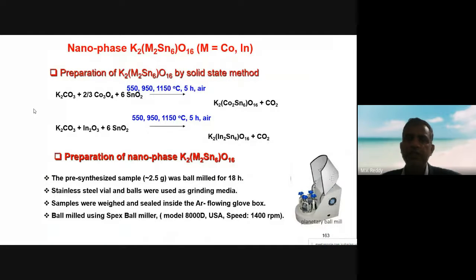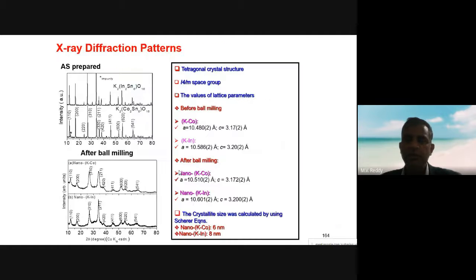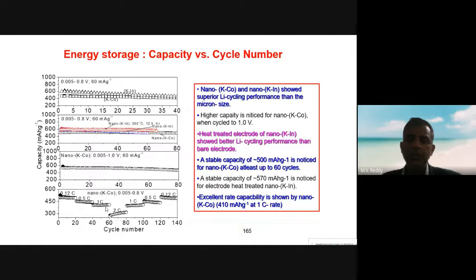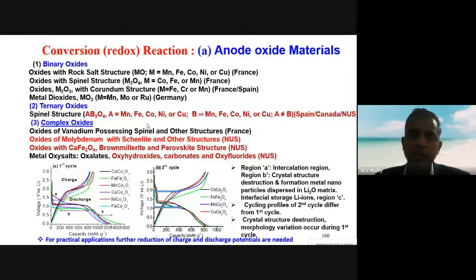Another example is the nanophase tin hollandites. You prepare the sample using the solid state method. Nanophase we can get by the ball milling approach. As prepared and after ball milling, you can see the difference in particle size reduction, and the capacity versus cycle number clearly shows that. This cobalt seems to be a good matrix element for lithium cycling.